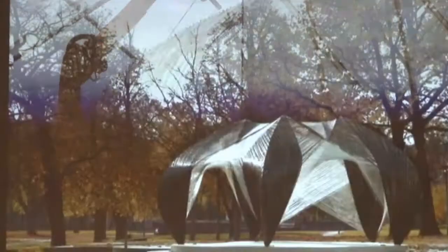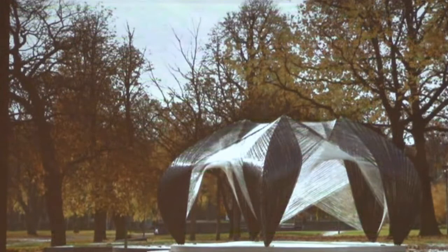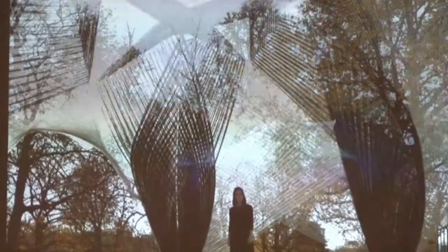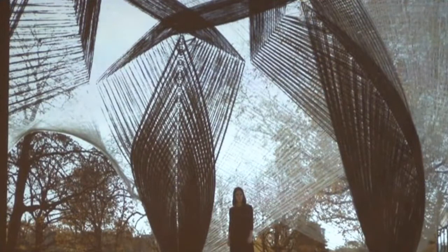In this case, the final shell consists of more than 60 kilometers of robotically laid carbon and glass fiber, but in its final state it is only 4 millimeters thin and extremely lightweight. The entire shell weighs less than 300 kilos, which means a ratio of less than 5 kilos per square meter, which in Germany is classified as an ultra lightweight structure. And I think that also becomes visible on the inside, where an outstanding level of transparency and intricacy of the resulting surfaces is revealed that almost makes the glass fiber surfaces disappear.